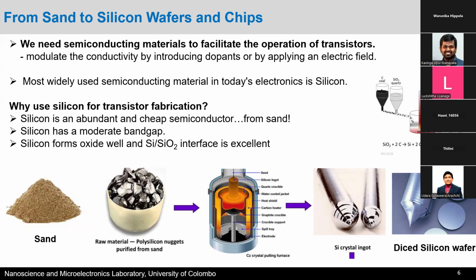So sand, what we actually do is we get sand from particular areas of the world where sand is actually ultra pure, and then we mix it with coal, and then we melt it, we liquefy it, we apply very high temperatures to make sure that it is liquefied, and then the carbon connects with the oxygen, and it forms carbon monoxide and carbon dioxide, while silicon is extracted, and you can actually extract industrial grade silicon, which is 99.8% pure out of this methodology, right?